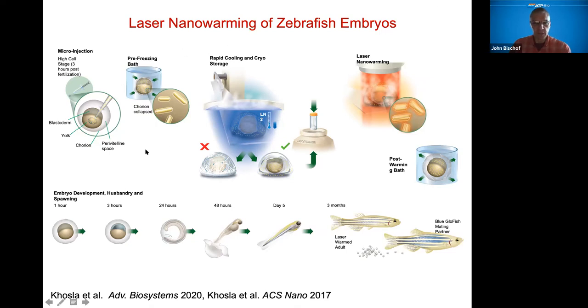And so this is just really laying out the method, and I won't go into gory detail here, but the microinjection piece is very, very important in terms of getting those gold nanoparticles into the embryo and spread around sufficiently. We then need to rapidly cool the embryos. If we fail, you can actually see the failures because you have crystallization. We can also see it transparent and glassy if we're successful. So that allows us then to store. When we want to bring out the embryo, we then laser warm, and we get this fast and uniform 10,000 C per minute or greater warming.